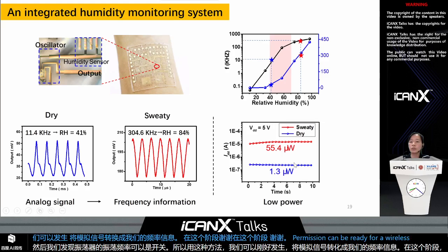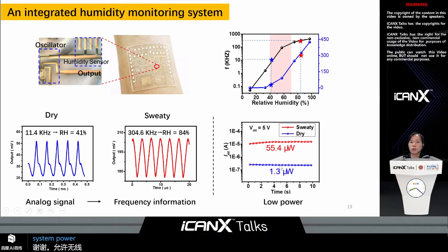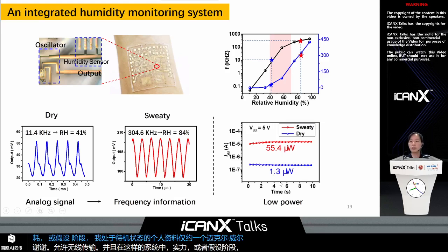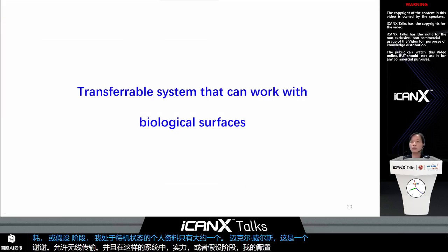And in such a system, the power consumption of the humidity monitor system in the active state is around 50 microwatts, and in the standby state is only about 1 microwatt. This is the first thing we have done.